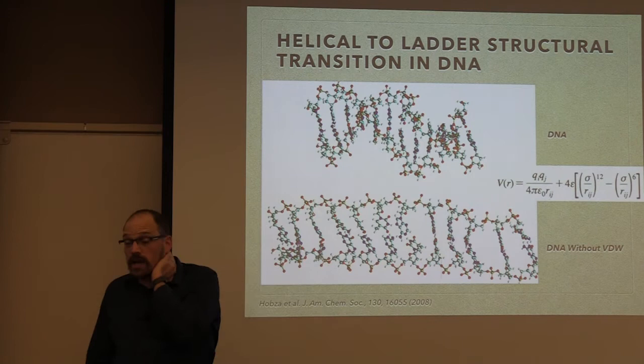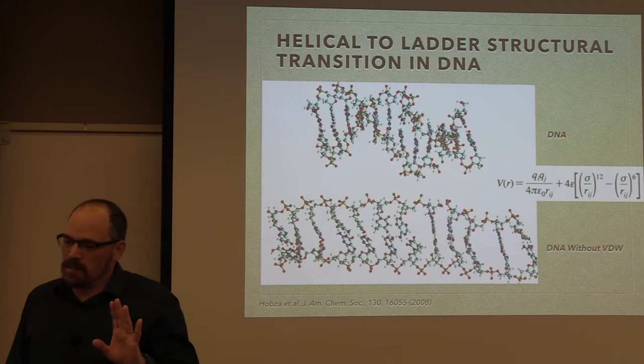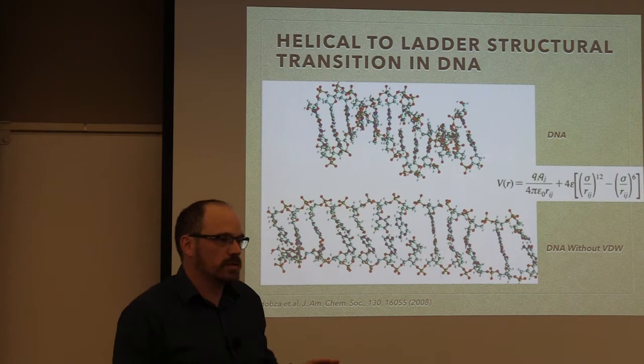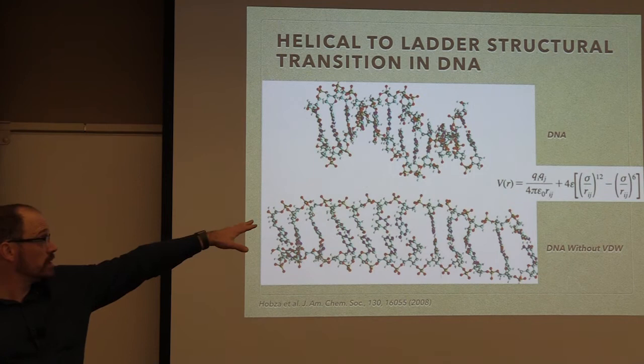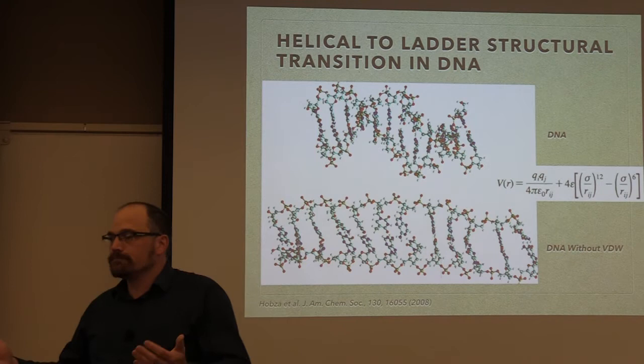There were two schools for Van der Waals corrections: one, mostly from Rutgers and Denmark, used theory — they came up with non-local functional corrections. Others came up with corrections to the forces. You may have heard of the Grimme approach, which essentially adds a Lennard-Jones type 6-12 interaction. By doing that, you actually get the structure right. The price to pay is adding some classical parameters, but with a good training set you get pretty good Van der Waals — good long-range forces.